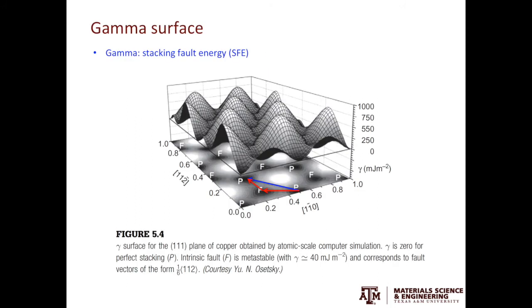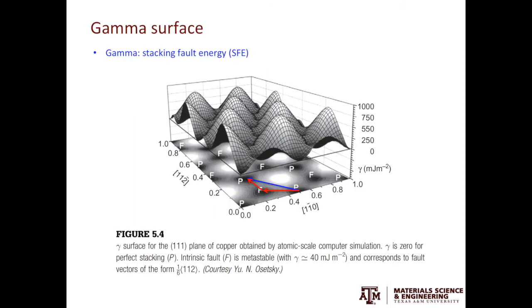Before wrapping up today's video, I'd like to introduce a new concept, which may help you better understand full dislocations versus partial dislocations. The new concept is called gamma surface. Gamma surface measures the energy of gliding one atomic plane on another. In this gamma surface of the 111 plane of copper, there are three major features. You have those hills or peaks. You have those saddle points like these. You also have the valleys.